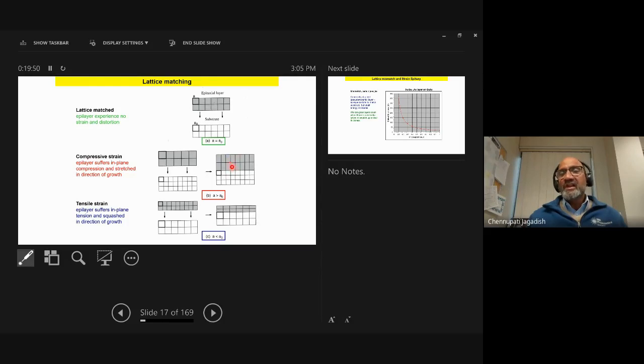And those dislocations act as non-radiative recombination centers. So it means light is not going to come out efficiently. But also, if you have a material with a smaller lattice constant with respect to the substrate, it expands, and again you create a tetragonal distortion here. It can grow up to certain layers, and beyond a certain thickness, which we call the critical layer thickness, it relaxes back to its original lattice constant. Again, it creates dislocations. So you can make use of this compressive and tensile strain up to a certain point, and strain also modifies the band gap of the semiconductors, which we also exploit, for example.